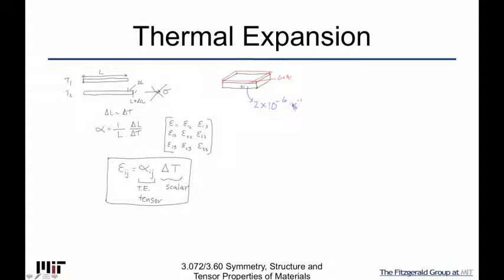And so you can see here that gallium arsenide is approximately 4 times 10 to the minus 6 inverse Kelvin. I mean, these are just rough numbers. So you can already see here that when I have hundreds of degrees temperature change, I'm going to end up with, say, 10 to the minus 4 strain, and 10 to the minus 4, 10 to the minus 3 strain.